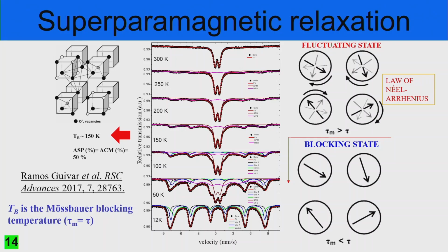We can prepare a reactor for the co-precipitation method, and we can check the stoichiometry to obtain high amounts of magnetic nanoparticles. And we can conserve the properties of nanomaghemite mainly. But after you make the treatment of the water, how do you take them out at the industrial scale? We think that magnetic separation will be promising. We have permanent magnets and, of course, low field and high field gradients that can be used, but it will depend on the energy employed for that. So permanent magnets can be an option.